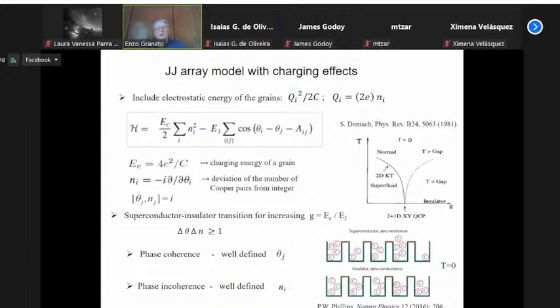To describe the system, we have to add additional terms to the Hamiltonian. The Hamiltonian so far only takes into account the Josephson coupling between the grains. But if the grains are sufficiently small, or the superconductivity is weak, you also have to take into account the fact that the grain has some size, and if the grain has some size, it has some associated electrostatic energy. The electrostatic energy is the total charge in the grain divided by the capacitance. The total charge in the grains is given by the deviation of the number of Cooper pairs from the average value, which is cancelled by the background charge. This term is written here. So the Hamiltonian now has two terms. This is the simplest possible Hamiltonian you can write to take into account this effect.